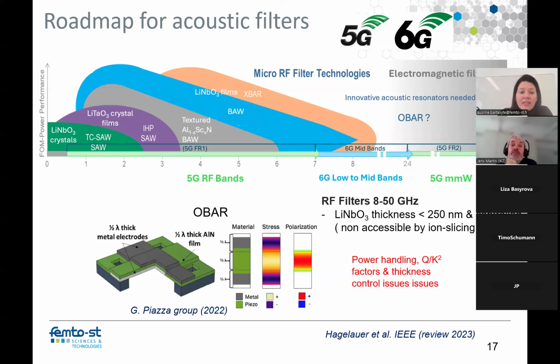And then other techniques like O-bar have been proposed, where you have 3 stacks with plus-minus polarization alternated, with periodic thickness polarization, which is done by bonding a film and polishing, or transferring, 3 times. This technique allowed to go to much higher frequencies and to overcome the problem of impedance matching, too-small resonators, and so on. So it's a very nice technology. But the problem is that you need 3 times the equivalent thickness. And already the bulk devices based on lithium niobate are too expensive. The price is quite high for industry. So to repeat the same thing 3 times becomes too expensive for the application.